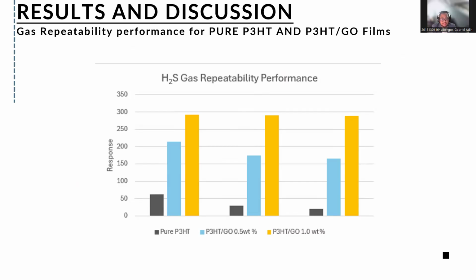At 1 weight percent GO, the sensor shows the highest and most stable response in all three cycles. This is due to the synergistic effect of the GO, which has a large surface area and functional groups that help absorb gas better. Also, there is a strong pi-to-pi interaction between GO and P3HT, which improves how fast and efficiently the gas sensor reacts to gas.